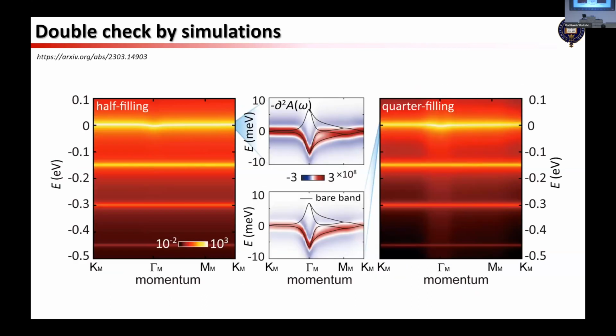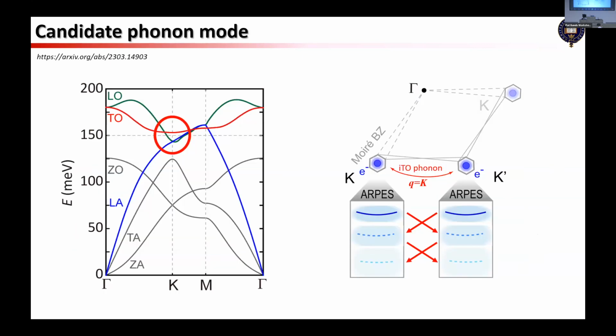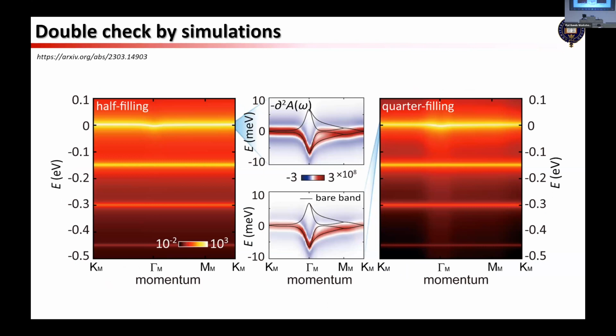So now that we have this phonon hypothesis, we went to do more calculations. We actually asked Yao Wan's group, since we found his paper in the previous STO2 deck, where he worked on the replica, and we asked him to do something similar in this system. Indeed his calculation shows that for different fillings, half filling and quarter filling, if we turn on this electron-phonon interaction coupling, you can see the replica separated by the phonon energy.